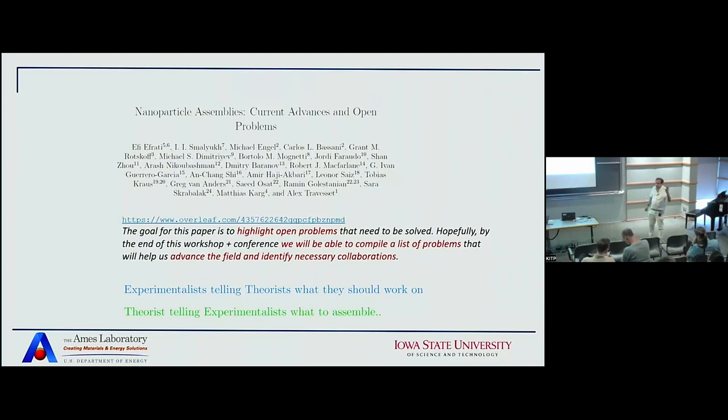And maybe for some of you it's obvious, but it wasn't obvious for me until we saw the simulation, which is that if you have a ligand like this, and this is very long, then the polymer will go around the nanoparticle and will form things like this. Because the ligand is sufficiently long to just go and engulf the entire nanoparticle. So those are new effects that take place when you have two nanoparticles.